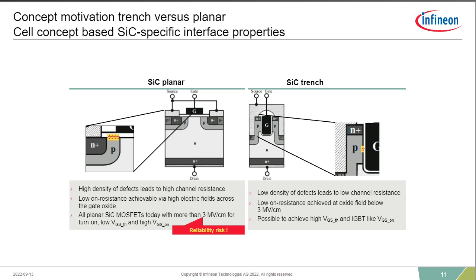Conversely, with the trench-based device, all of your P region happens in the Y direction, so a vertical direction on your screen. The processing equipment and defect ratio of silicon carbide in the Y direction is significantly lower, which allows you to have a much smaller overall cell structure for a trench-based silicon carbide MOSFET. That allows smaller die sizes, better economies of manufacturing, and higher yield rates as well, because defects can happen anywhere in the map of the silicon carbide wafer. If you have a smaller cell structure, fewer devices are affected. So overall, your yield will be higher with silicon carbide trench-based devices.